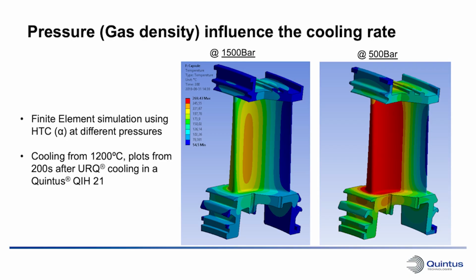Okay, and do you see a difference then at different pressures as well? I mean, do you see any changes in the cooling rates based on pressure? The convection or the heat transfer coefficient increases with the pressure, or actually the density of the gas. Okay. So we will not reach water in heat transfer coefficient, but it's much better than normal atmospheric pressure air. So it's very similar to high pressure gas quenching.